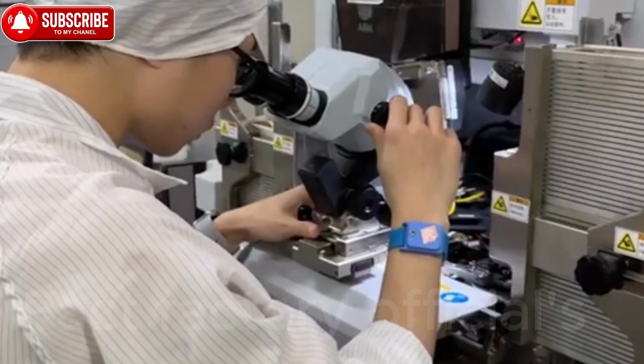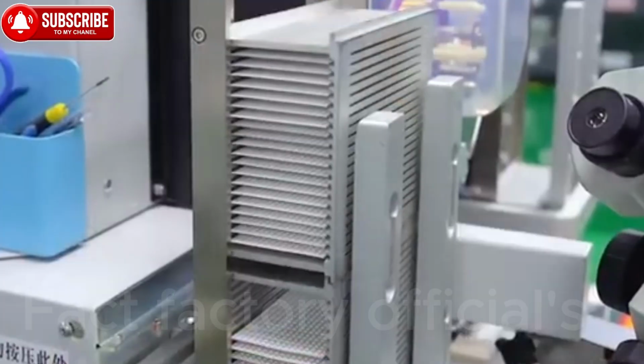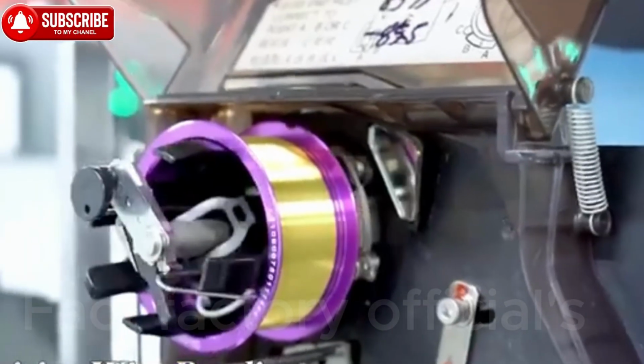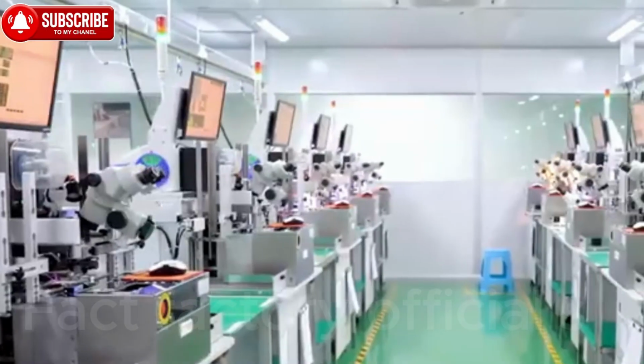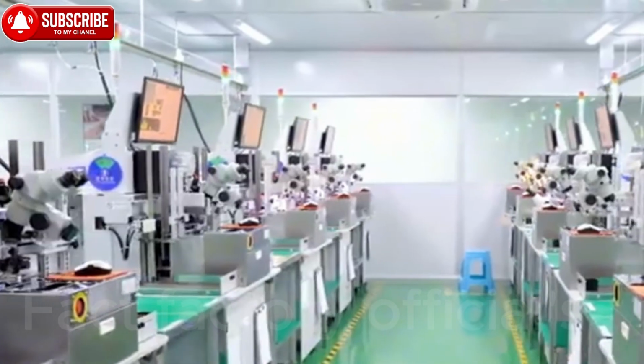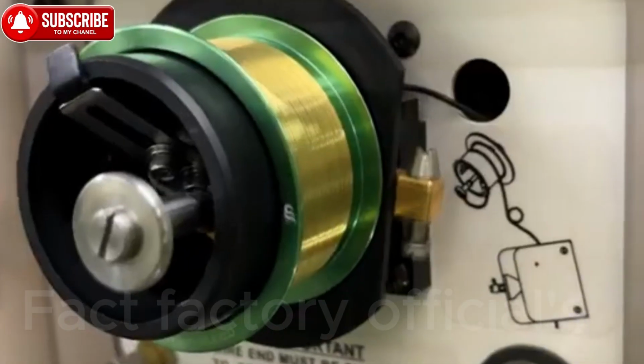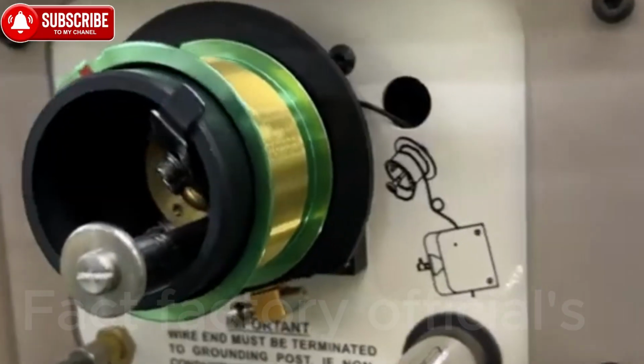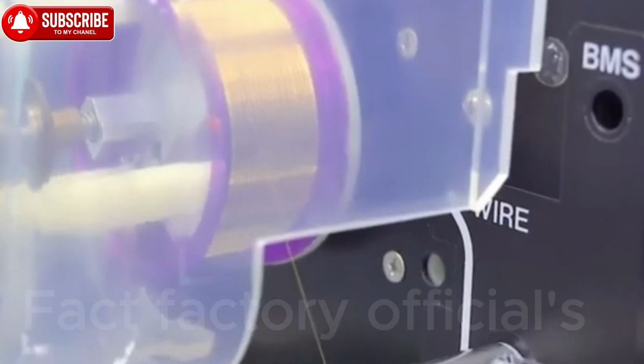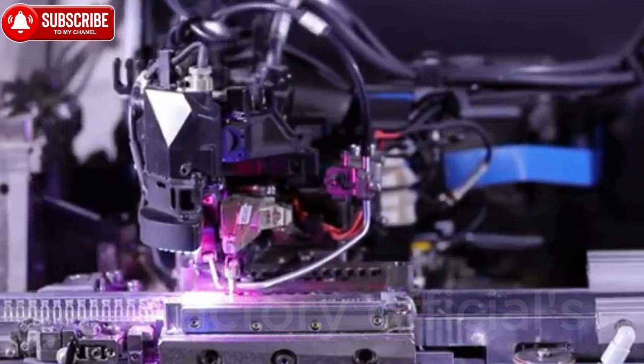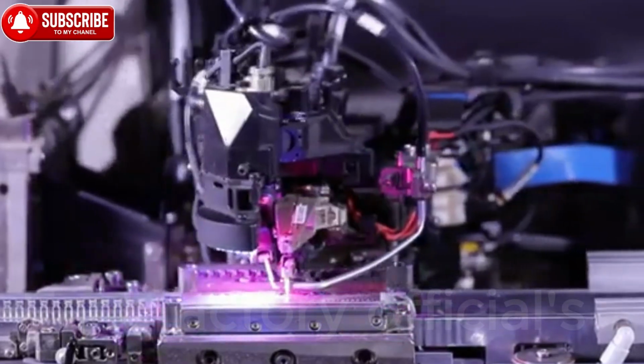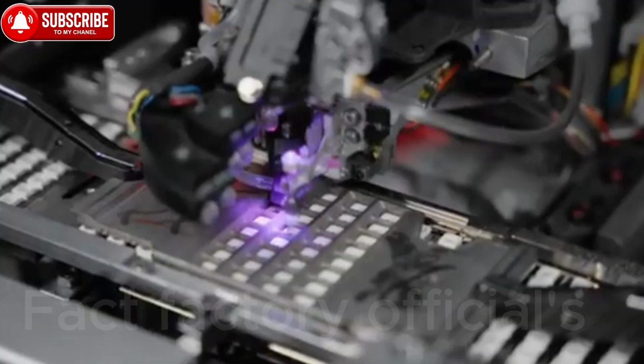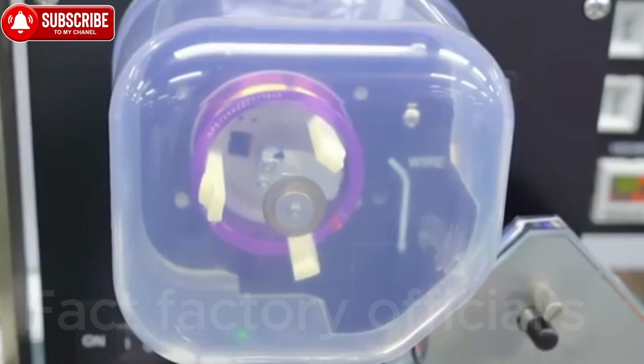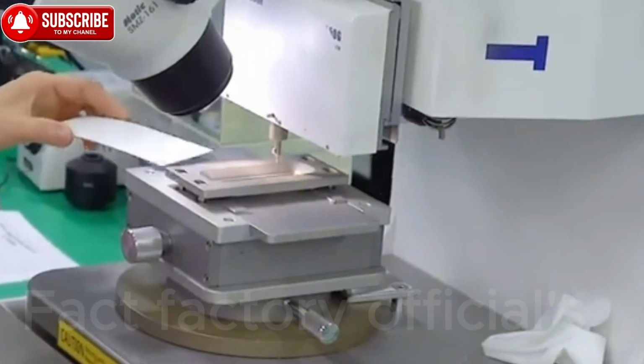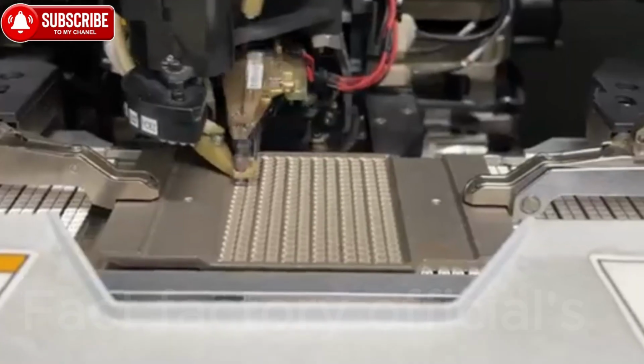This ball is pressed onto the chip's electrode, creating the first bond. Immediately afterward, the wire is drawn into a carefully shaped arc and lowered onto the metal lead to form the second bond. Then, the wire is cut and the machine moves on to the next chip. This process operates at extremely high speed, yet each step must maintain uncompromising precision. Each gold wire loop is tightly controlled in terms of loop height, adhesion strength, and tensile force to ensure reliable electrical connection and long-term stability.